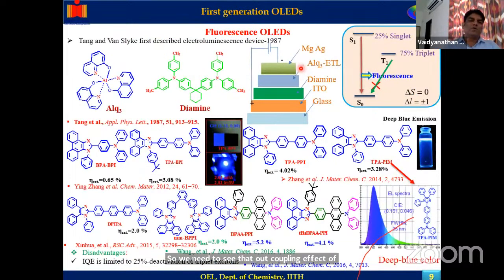Okay, these are the fluorescent molecules that have been discovered in the literature. We can see donor-acceptor molecules given here. The electron-rich triphenylamine can be used as a donor. The electron-deficient imidazole ring can be used as an electron-transporting material, or the acceptor. So more or less, you get only around 5%. So only 5% is restricted.